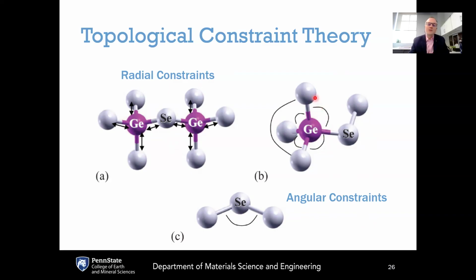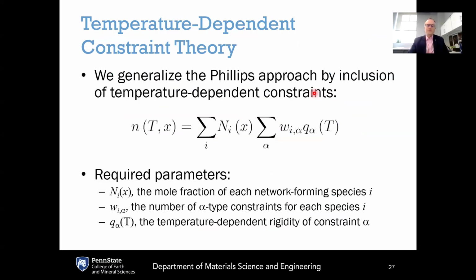So every one of these atoms here has 3 degrees of freedom if it exists in 3-dimensional space, because each atom can move in the x direction, the y direction, or the z direction. Every time you subject this to a rigid bond, it takes away one of those degrees of freedom. And if you have a number of rigid constraints exactly equal to the number of degrees of freedom, then you've got a perfect balance. And this is what's called an isostatic system. And Phillips postulated that this would be the best glass forming system. And a lot of work had been done to validate or to test Phillips's theory.